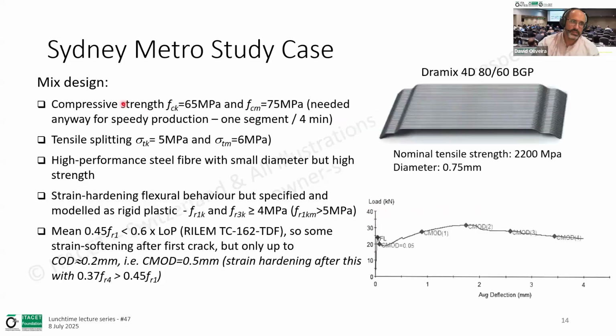The first thing we looked at is our segment design. We were originally adopting a 50 MPa concrete, like Varia showed as well. But the contractor was already specifying for his segment a much higher concrete strength, not because we told them that would be needed, but because he wanted to be demolding very quickly. He was targeting to produce one segment every 4 minutes, and therefore he was using a much higher concrete strength, with a characteristic value of 65 MPa and a mean value in the order of 75. When we got that information, we thought we might as well use it. If we have that strength, we might as well take advantage of it and not just throw it in the bin. And that also allows a slightly higher tensile splitting strength, which we can start to use.